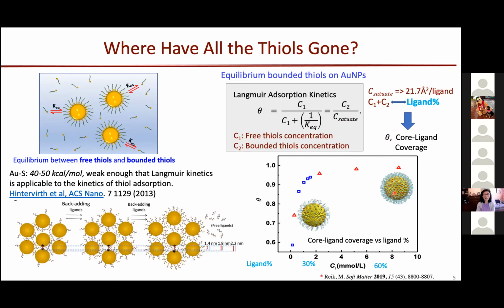This relation tells us that as you remove thiols, the gold becomes more and more bare, and eventually the particles stick together. I'd like to point out that the 30% threshold I mentioned before, above which the film loses its elastic property, corresponds to about 90% coverage.